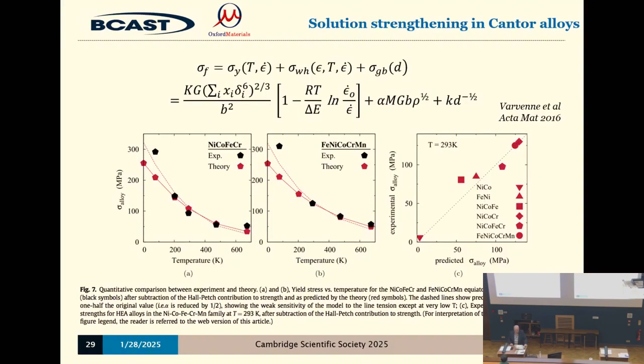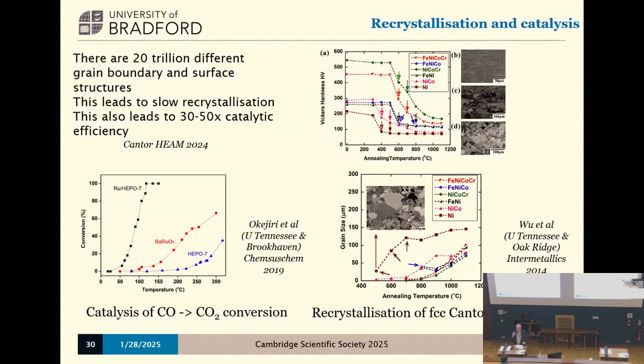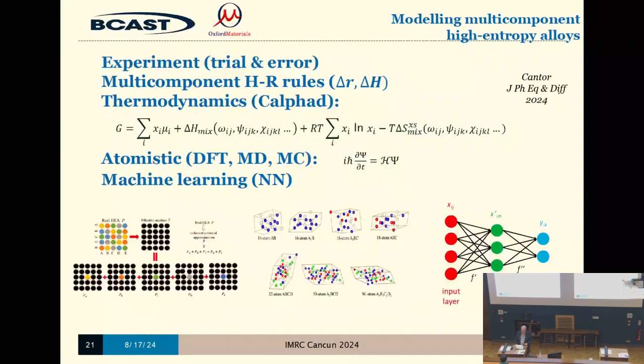And the theory and experiment of this is quite complicated. I'm not going to go into the details, but it gives quite good results. Finally, the same thing happens with local surfaces inside the material. Most materials have several crystals inside them, and they have surfaces, and it turns out they've got great catalytic behavior because there are 20 trillion different structures on the surface. So you get much higher catalytic efficiency because you've got a wide range of different energy sites at which catalysis can happen on the surface. I won't bother with that.